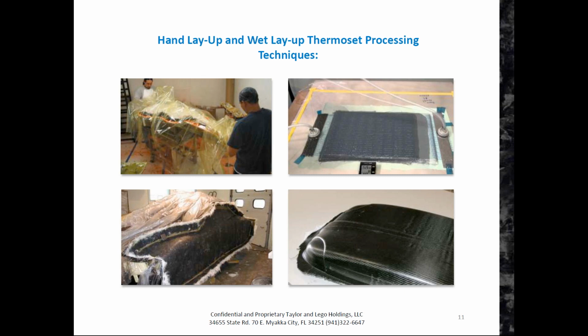And not only that, because of the inaccuracy, the parts are going to be very difficult to trim and post-process afterwards. Now, if the parts are small enough, a lot of people are taking these molds in the vacuum bag systems and putting them into an oven, and they're still only at 1 atmosphere of pressure, but they're causing the resin to kick faster, obviously, by applying more heat. So you can get the parts a little faster in as little as maybe 2.5, 3 hours per part, but you still require that trim. So on a very complex part, you could spend all day to get 1 part. And this is what is being done 80% of the time around the world.